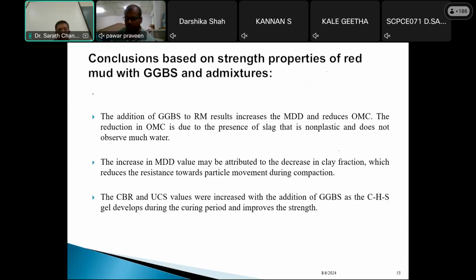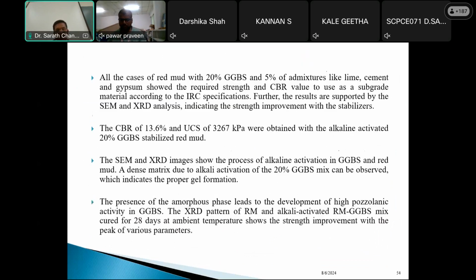Conclusions based on the strength properties of red mud with GGBS and admixtures. So here, GGBS, along with the admixtures, helped to increase the strength of red mud, and a CBR of 13.6% and a UCS of 3,267 kPa were obtained with the alkaline activated 20% GGBS stabilized red mud.